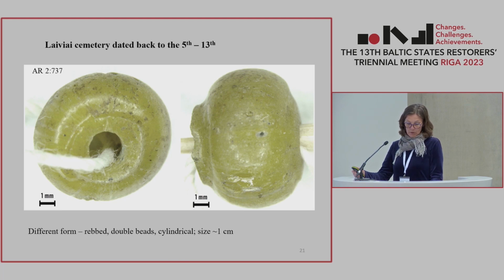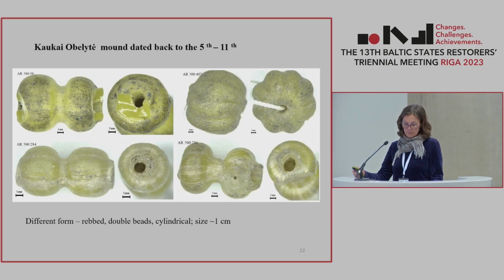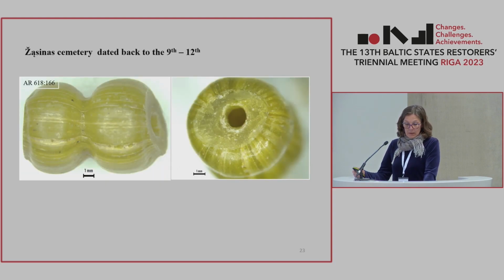The main question that arose was, why does the condition of glassy beads vary so much if compared with those described before? From the presented images, we can see point destruction damages of the surface of the beads, layer of glass formation, and uneven distribution of yellow particles. The same combination of instrumental analysis was applied as for yellow opaque beads.